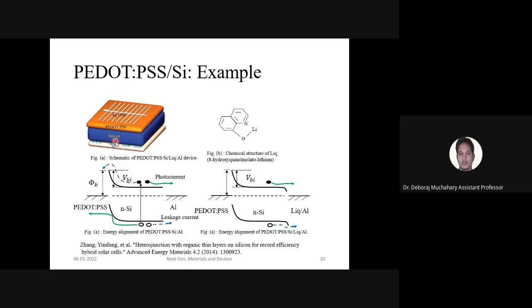What is the advantage of using this? Again, the reduction in the defect density. So the defect density at this interface, or this back junction, back contact, that is actually a back contact. At this back contact, the surface recombination on the silicon surface is high, and that is why the efficiency will again be falling down. So that is why they have used this LiQ layer, and this is the schematic of the energy band diagram.